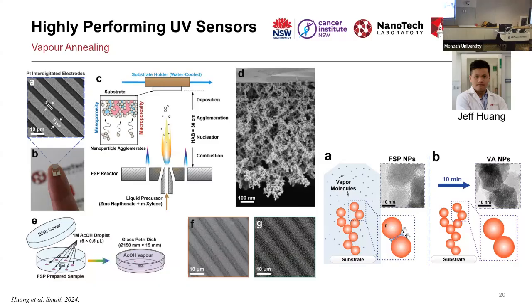It's a Petri dish, and we put 6 droplets of 0.5 microliter of 1 mole acetic acid, which is quite similar to vinegar. It's a very diluted vinegar. And we close the lid. What happened here is that we let these droplets, which are significantly small, evaporate inside the Petri dish and create a vapor-saturated environment inside the Petri dish.